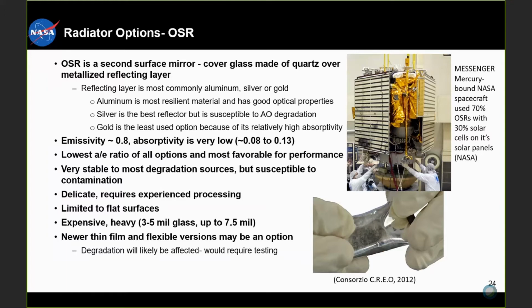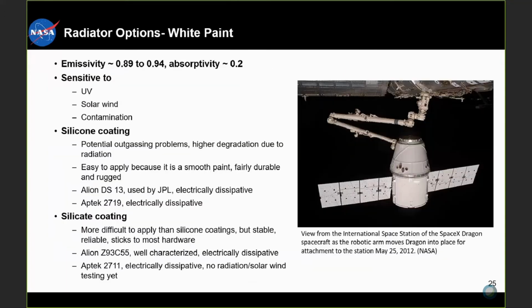So you'll see most OSRs have a high emissivity and low absorptivity. Emissivity value is about 0.8, and absorptivity is very low, around 0.08 to 0.13. Ultimately, the lowest absorptivity to emissivity ratio of all options will have the most favorable performance. OSRs are very stable to most degradation sources, but they are susceptible to contamination. They are also delicate and require experienced processing. They're limited to flat surfaces, and they're also expensive and heavy. There's also another option made by Creo, which is a newer thin film, a flexible version that may be an option. It's applicable directly onto spacecraft external surfaces. Although degradation will likely be affected, so it will eventually require testing. Next slide, please.